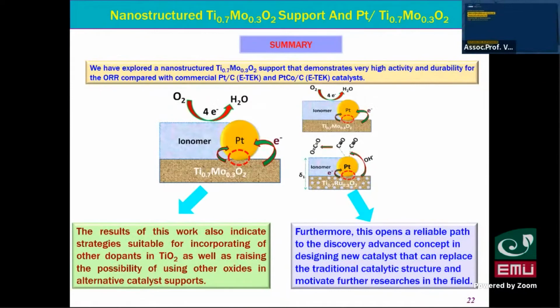So we have a summary for this idea. We have explored for the first time the new material, molybdenum doped into titanium oxide support, which can enhance the activity and durability for the ORR compared to the commercial Pt on carbon and Pt-cobalt alloy on carbon catalysts. This is the scheme to show the idea - we can see the interaction between the titanium molybdenum support and platinum, due to electron transfer from our support to platinum, which enhances the interaction between the Pt and support.